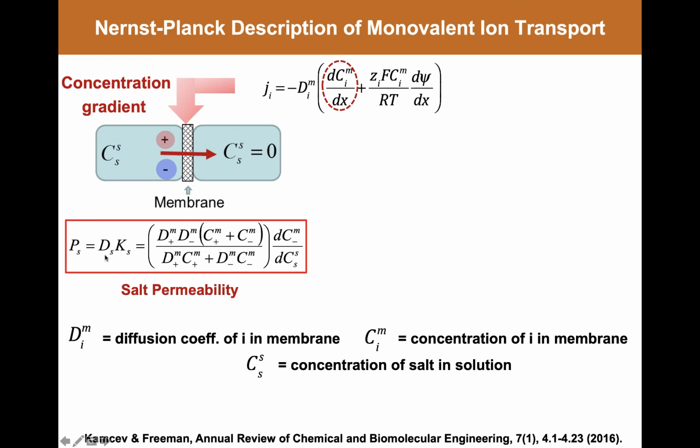So this looks exactly like the expression that we use to describe gas transport through polymer membranes, where we said that P is equal to D times S. Here in the aqueous and salt world, the nomenclature grew up somewhat differently, and so instead of saying that P is equal to D times S, we say that P is equal to D times K, where K is the solubility or partition coefficient of salt into the membrane.